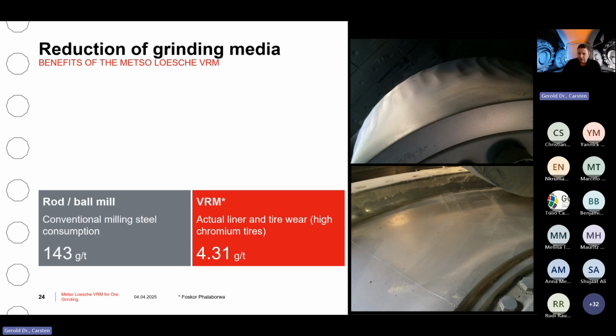Speaking about grinding media consumption, in this case, it's a plant where a Loesche VRM is operated in parallel to a rod mill ball mill plant with a tertiary crusher in advance. And here we utilize high chrome grinding elements. You see on the top right the grinding tire, in the bottom right the grinding track. And high chrome is, let's say, the lowest quality that we use.